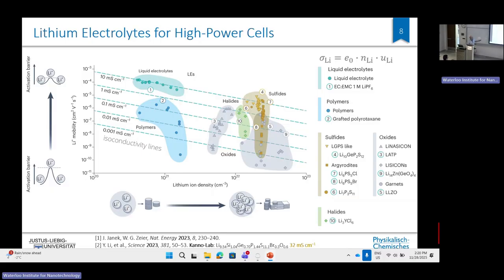It's a bit deceiving with the liquid electrolytes, because this is the total conductivity of liquid electrolytes, where the cations only transport, let's say, 30 to 40% of the charge, because the anions are relatively more mobile than the cations in most liquid electrolytes. In the case of all the inorganic solid electrolytes, this is really pure cationic conductivity. And you see here are the sulfides. They can climb up quite high here. So this is the 10 millisiemens per centimeter line, which I think has to be met. Otherwise, you will not be able to have thick electrodes. If you go to lower conductivities, you will have too high overvoltages in your electrodes, and you will not be competitive with a good lithium-ion battery.